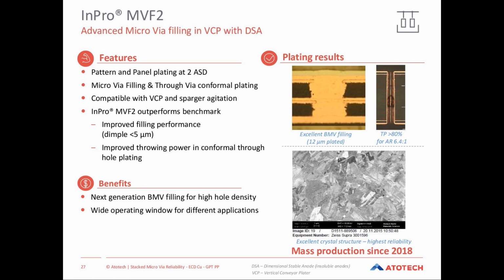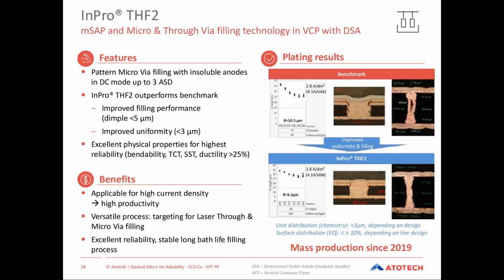In this way, you can combine copper filling and through hole plating with really excellent results due to the increased acid concentration we can use with this process and still have a very good copper filling with a very low plating thickness on the board surface. This combination is really impressive and gives you many advantages at once.